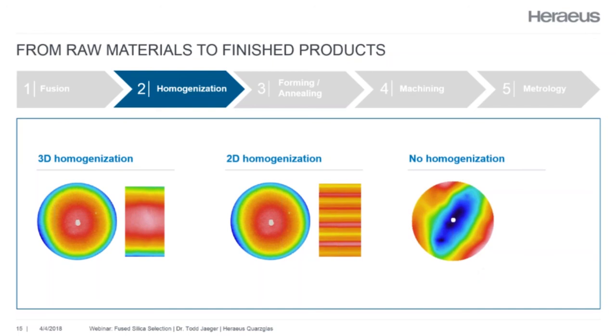So we correct for any of these inhomogeneities through this proprietary process, which is really a mixing process. Without getting into too great a detail, the material is heated up again and utilized in our special machines where the glass is actually mixed with itself. So if we mix it one time, for instance, we would get what we call a 2D homogenization. So this means that it's homogenized in the functional direction. So if we were looking at this interferogram and it was a window, this would be the direction that the light passes through. And this would be the direction on the side, so orthogonal to the functional direction.